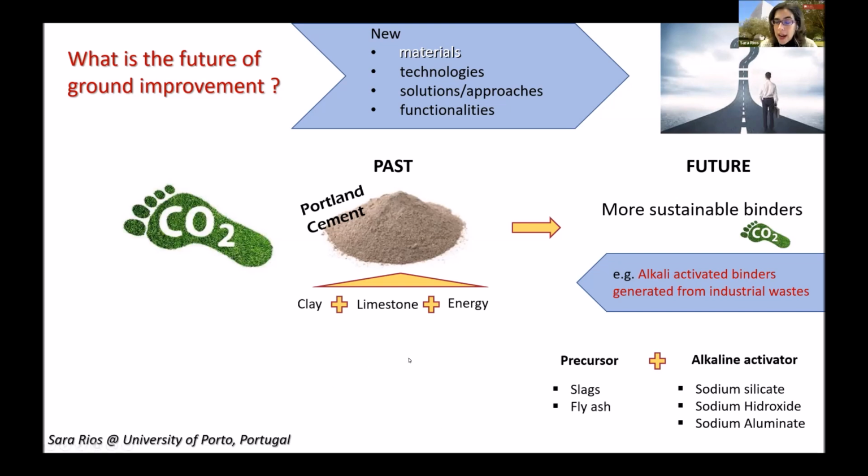But of course, there are some slags that are more reactive than others. For example, the ground granulated blast furnace slags are much more reactive than, for example, the ladle slag that I will show you in a few slides. So depending on the slag, some slags are more reactive than others, and that makes a significant difference.